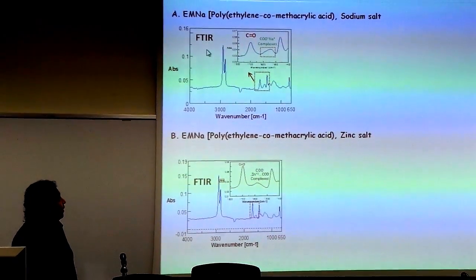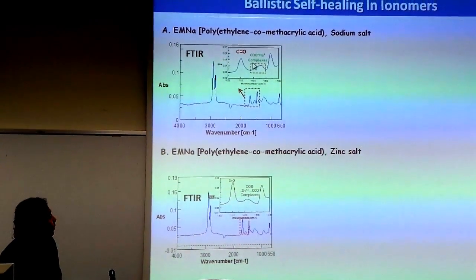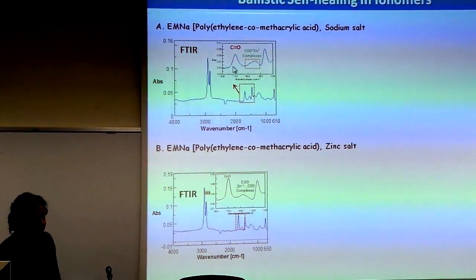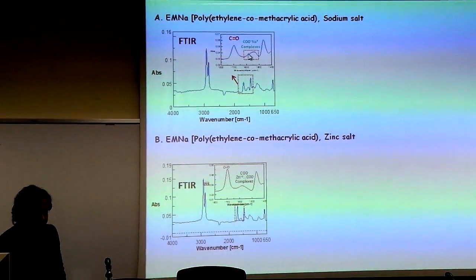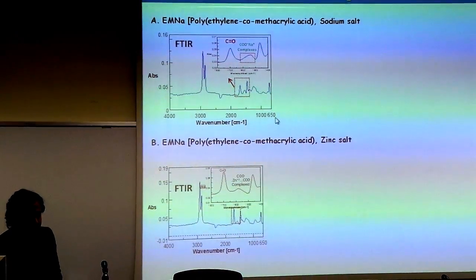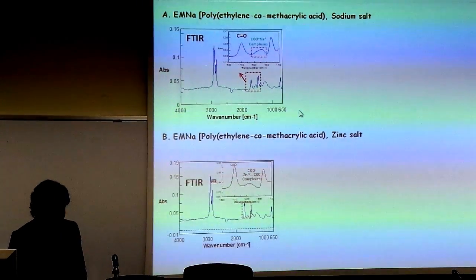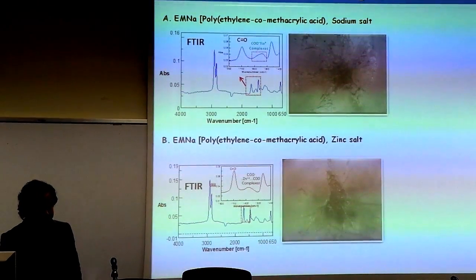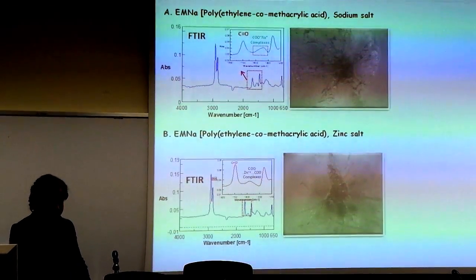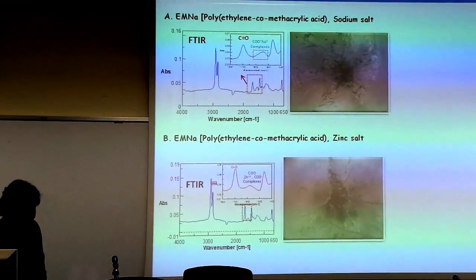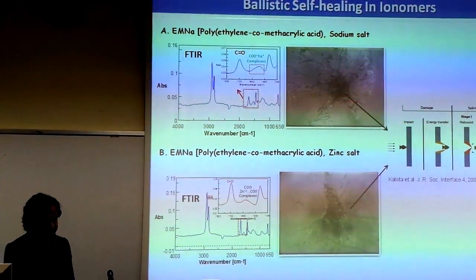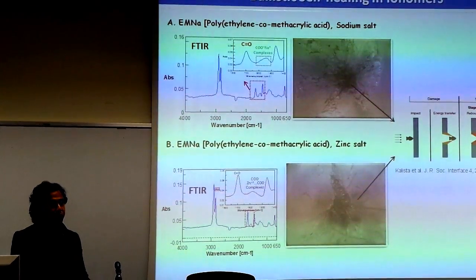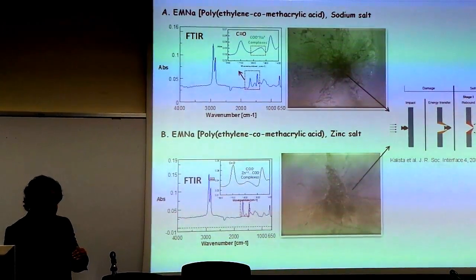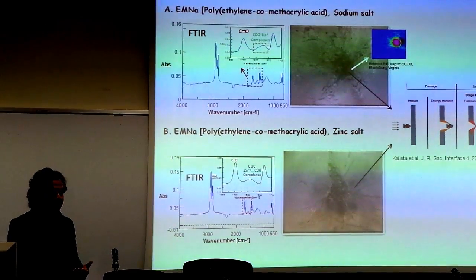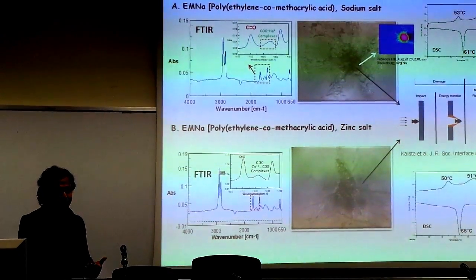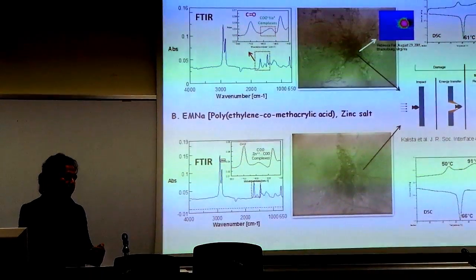At the beginning, I studied their chemical structure by FTIR analysis. I observed both the ionic aggregates and the carboxylic acid groups. And I should mention here that the ionic aggregates are very important for the promising thermal and mechanical behavior of ionomers. I also studied their ballistic self-healing behavior. And in the ballistic self-healing evaluation test, both of them showed self-healing as it was expected. As it was proposed by Stephen Kalista, during the bullet penetration at the impact zone, there is a temperature rise at the damaged zone, which is about 110 degrees Celsius. And in my DSC study, I found that this is actually 15 to 20 degrees Celsius above the melting point of the pure copolymer.